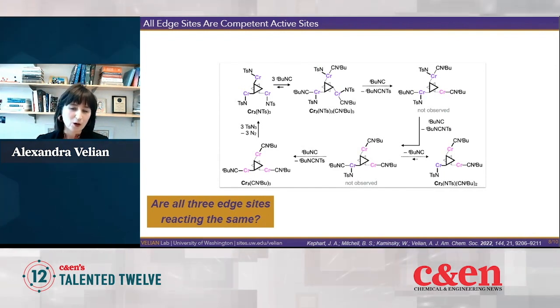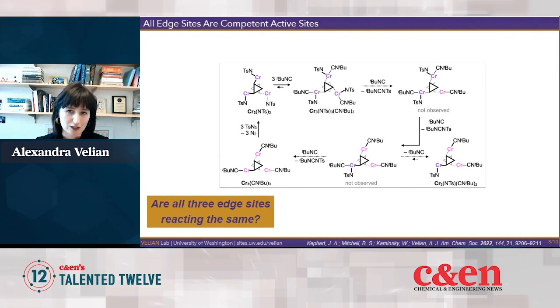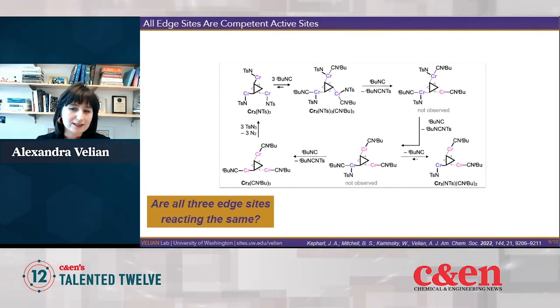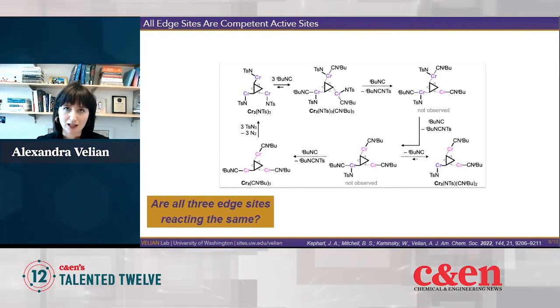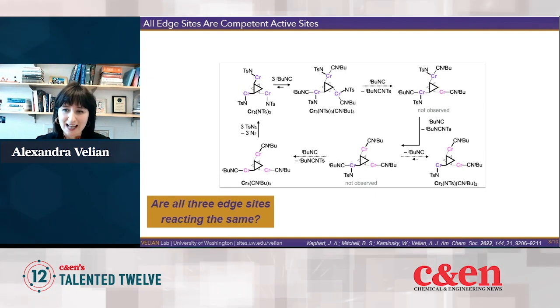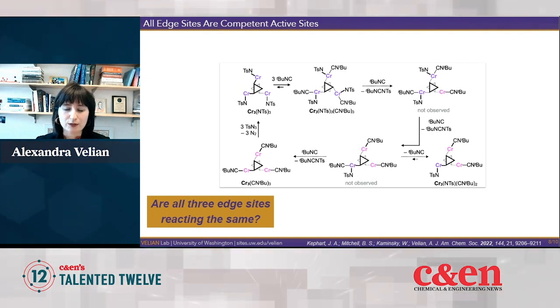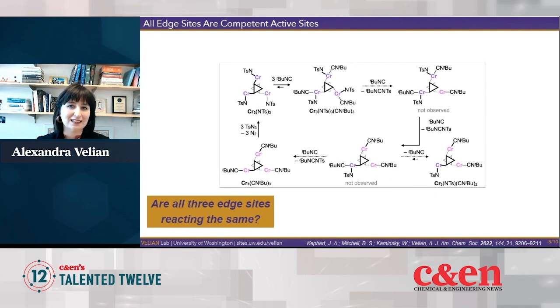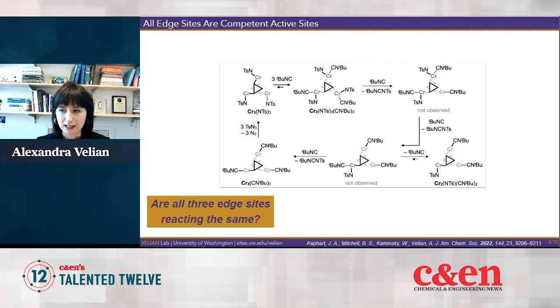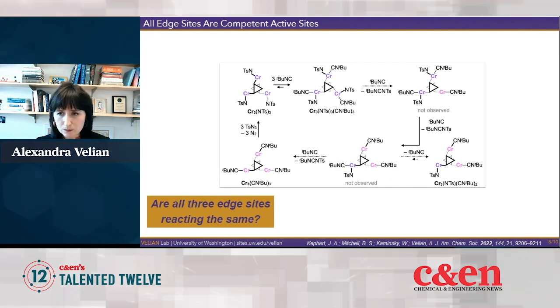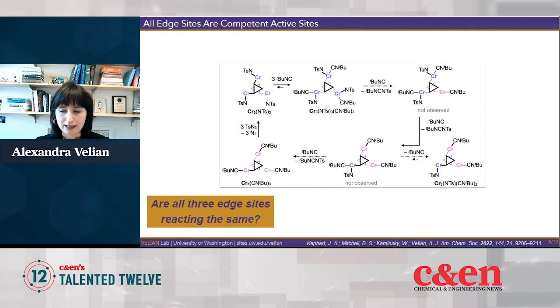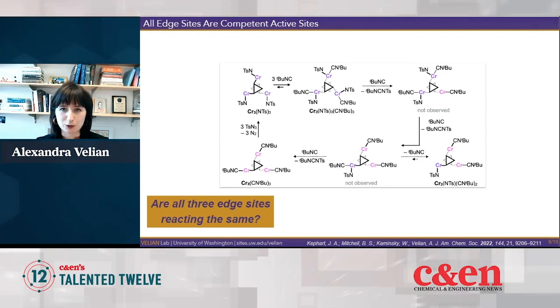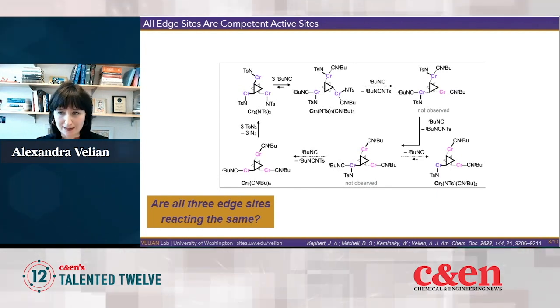Now, at a single edge site, we can envision how this transformation occurs. But if we consider all three at the same time, there's a lot of complexity that emerges. And so into sequentially activating the azide and then transferring it to the product, to form the product and reveal the chromium-2 sites in the process.